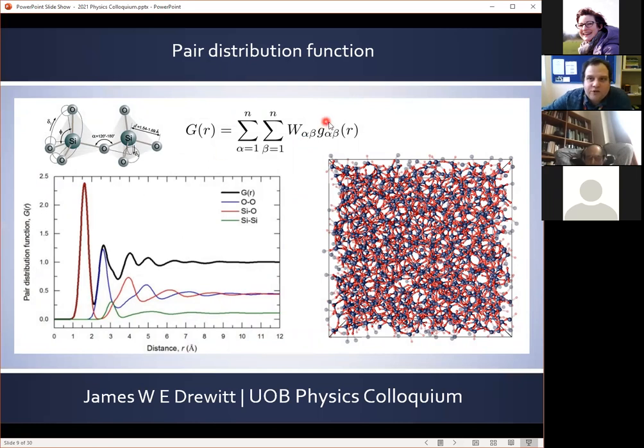So a little bit more information about the pair distribution function is shown here. As for the total structure factor, the total pair distribution function is the weighted sum of all the individual pair correlations in the system. So shown here is the pair distribution function, G(r), in black, for this simulated SiO2 structure. And we can see that the first peak arises from our nearest neighbor silicon-oxygen bond distance, with a second peak arising from the oxygen-oxygen distance in a SiO4 tetrahedron. At higher distances, we have overlapping silicon-silicon and other higher order correlations. And so experimentally, it's difficult to resolve these individual correlations beyond the first coordination shell.